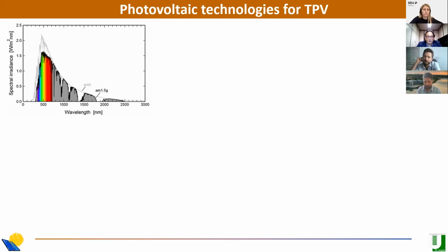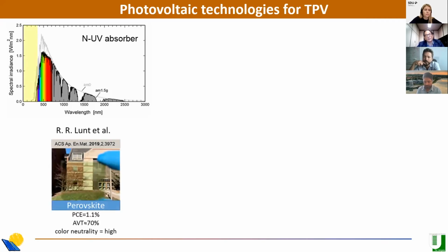So there are several technologies to integrate photovoltaics in semi-transparent facades. For example, I show you the spectral irradiance, so the sun spectrum we receive on the Earth. You can see that to make something which is transparent, but at the same time converts some light into energy, we can use, for example, the near UV part of the spectrum. So you have a near UV absorber. And in fact, there are already some reports showing that you can use this part to make a cell with some efficiency and an average visual transmittance, AVT, of 70%, for example.